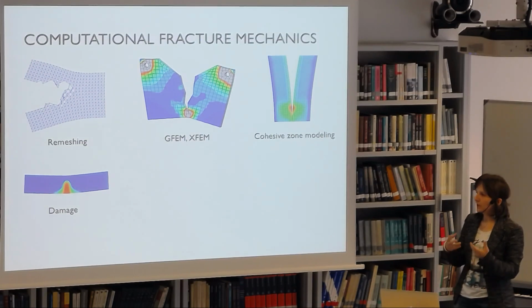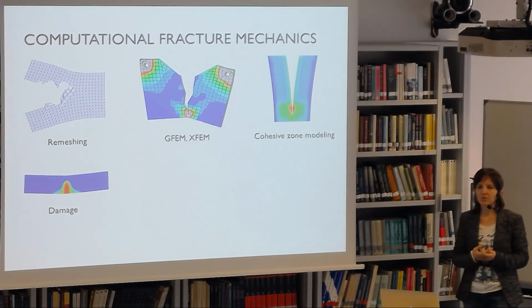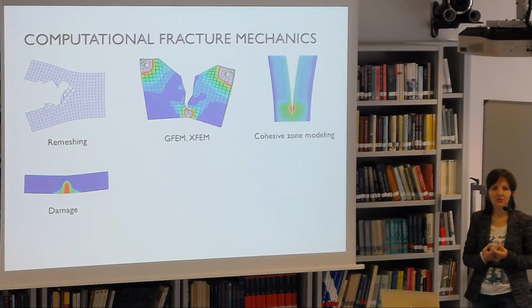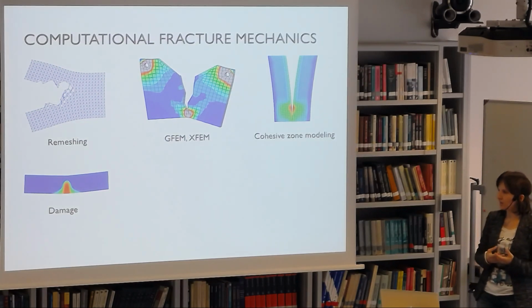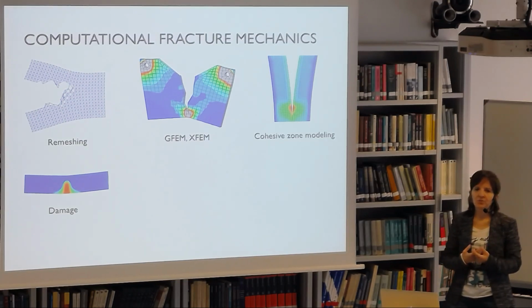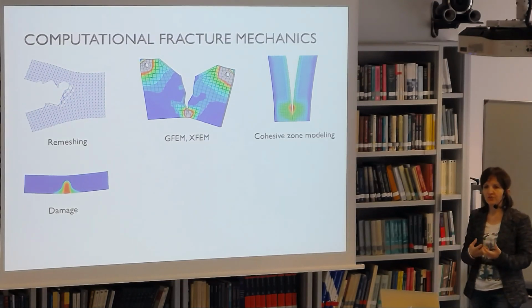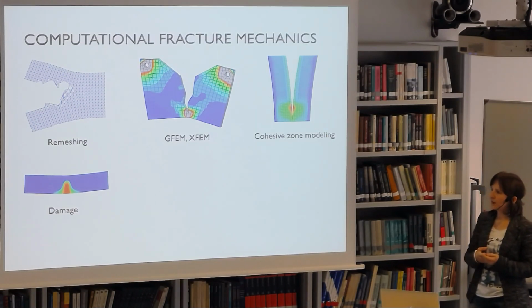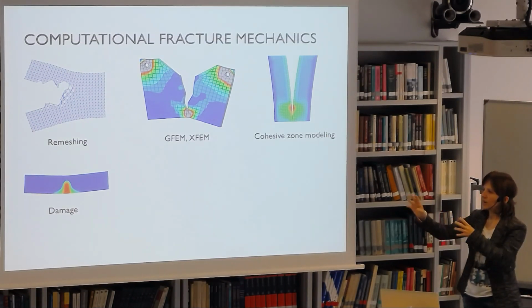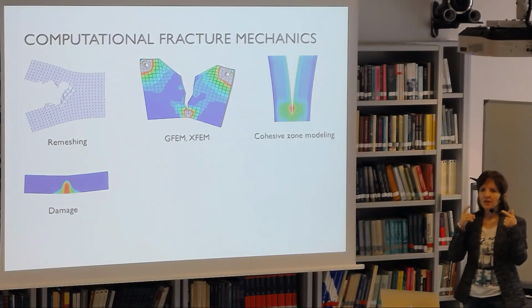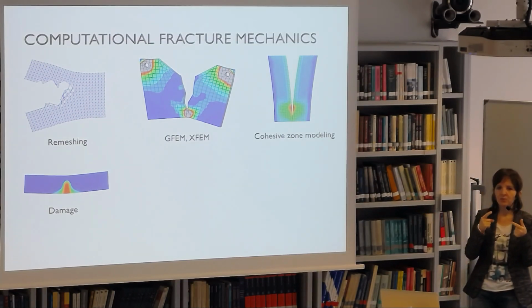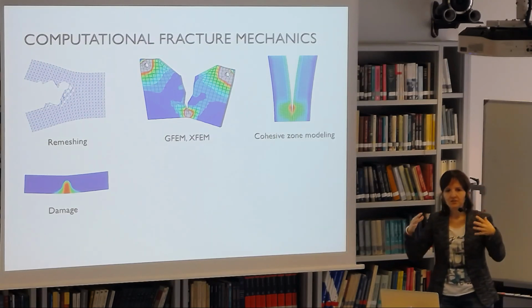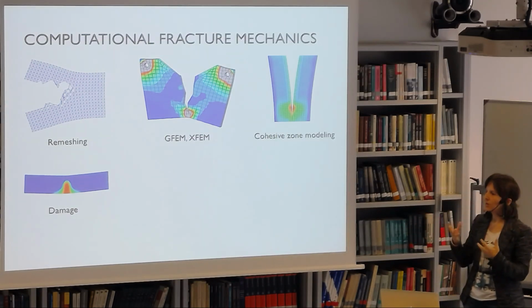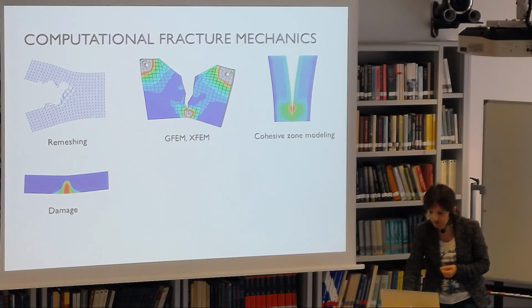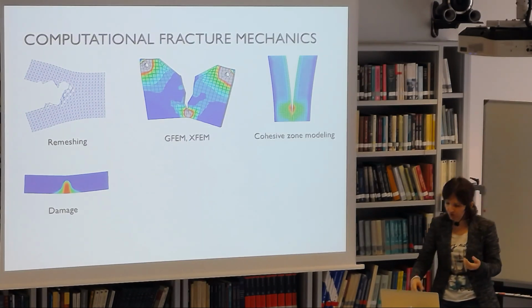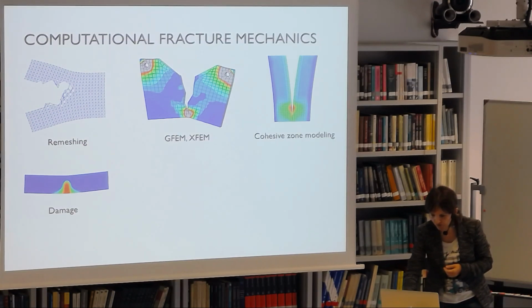And then there is a big family of damage approaches, and what we call the phase field approach to fracture is actually one special category of damage approach. But not all types of damage approaches really have all the features we desire. For instance, there are categories of damage approaches where the damage pattern, which you can then consider to be an indicator of where the crack is going, gets fatter and fatter as the load progresses instead of propagating. So there are so many approaches there that it's difficult to classify which ones have really desirable features and which not.